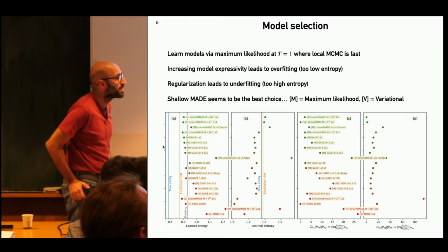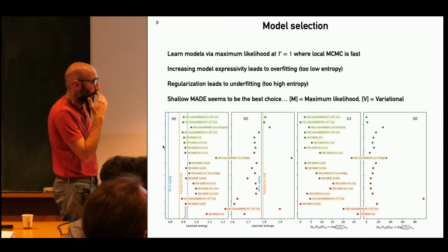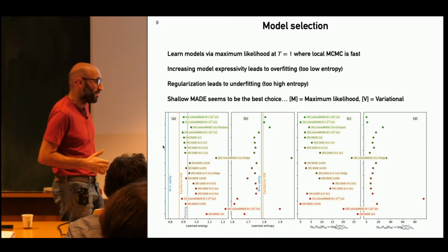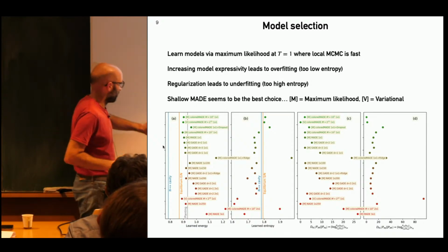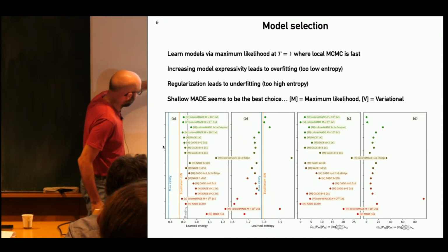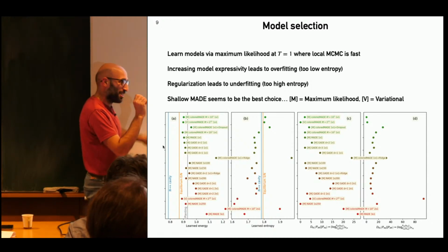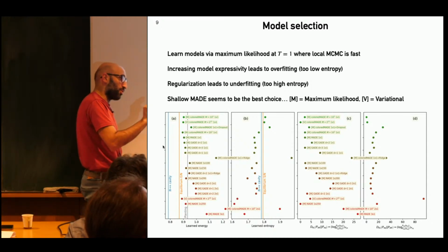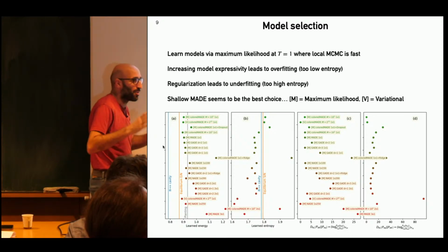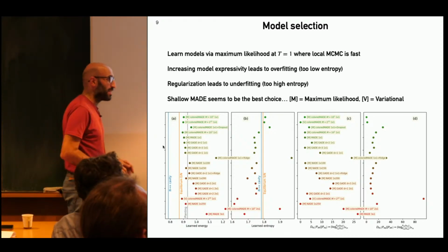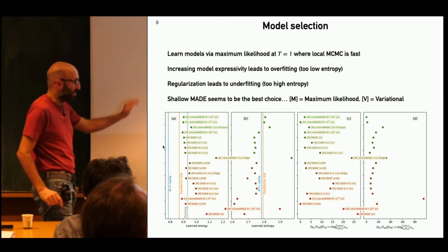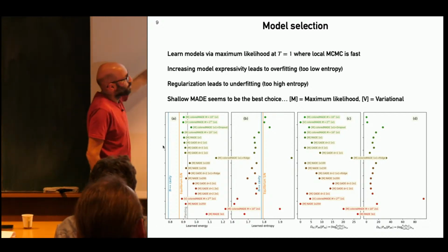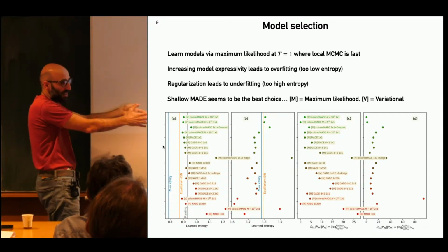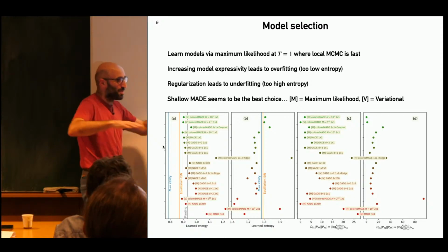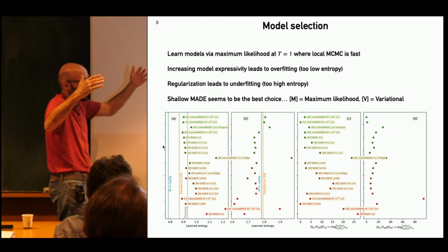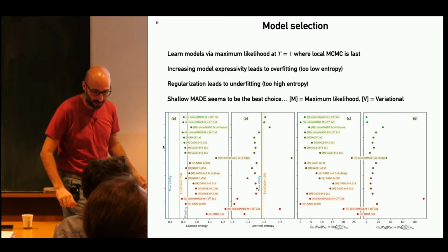Yes? Sorry, Francesco, I'm a bit lost there. Why is the energy increasing? You're doing the Boltzmann reweighting, so it should always give the right solution. No, sorry, right. This is the energy without the reweighting. We just want to test how well the model is learning the true one. If you do the reweighting, then it should be the same. But the problem is if you put dropout, for example, if you put regularization, what happens is that the model tries to have a bigger entropy, but also sacrifices the energy, and so it doesn't look good.